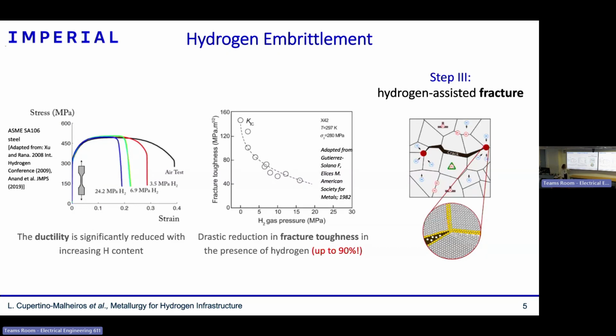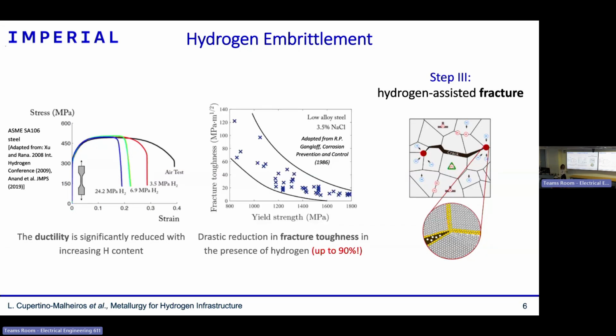And this is not even the worst example. One thing is if we go now for higher strength steels, and this is interesting for us because if you go for high strength steels, for the same application, if you have some load bearing capacity that the structure can resist, now you can use smaller sections and use less steel, which is more sustainable. And if you do go for higher strength steels, what you can see here on the graph in the middle is that, for the same environment, this decrease of fracture toughness is proportional to the strength of the steel.